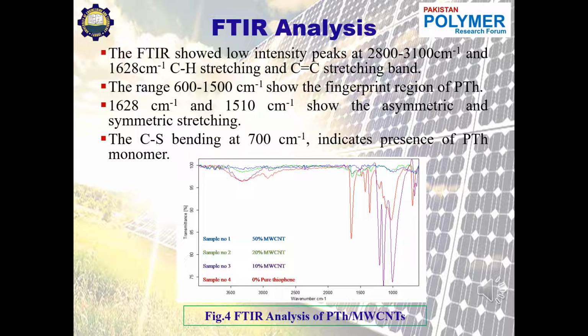Peaks obtained at 1628 per centimeter and 1510 per centimeter as well show the asymmetric and symmetric stretching of bonds. Here another sharp peak was obtained at 700 per centimeter, which indicates the presence of thiophene monomer.